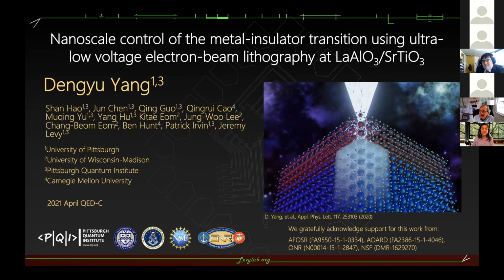I had a question. How thick was the LAO? Three unit cells. So around 1.2 nanometers. And it's like commercial STO substrates with LAO grown on top? Yes, exactly. We do a termination on the STO to make it TiO2 terminated, to make sure of the quality of the 2D electron gas. But it's a commercial STO substrate, and it's the PLD-grown LAO on top.